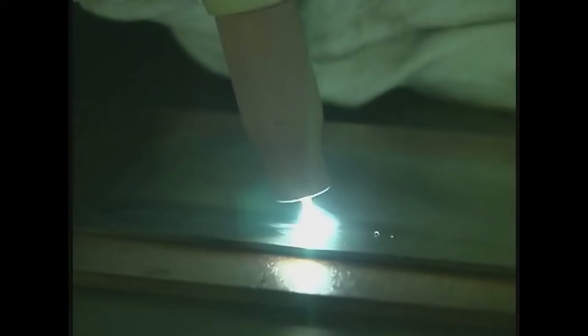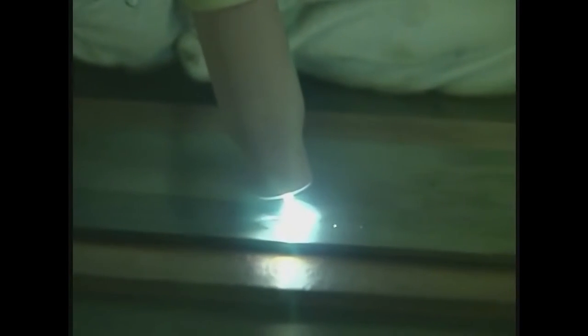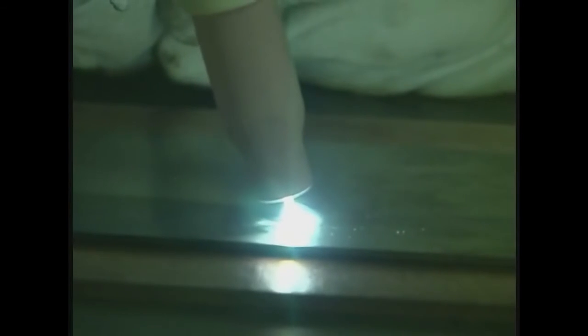Your goal with running a bead is to keep the width of the puddle uniform. The faster you go, the narrower the bead will be. The more heat you apply, the wider the bead will be. Often, as the part you are welding builds up heat, you'll have to either let up on the foot pedal or move the torch faster to keep the width of the weld bead uniform.